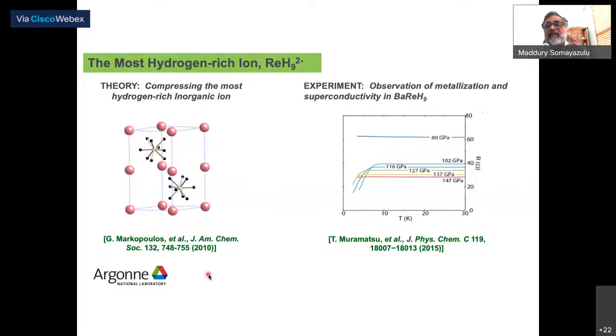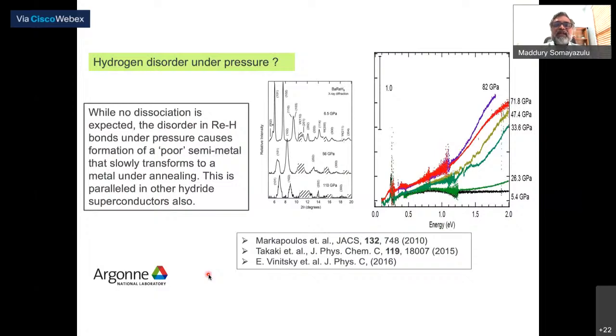But you realize that with increasing pressure, there are nebulous signatures of superconductivity, but not so superconducting. I mean, as you can see, the curves presented here seem to indicate that you do get a transition where the resistance is dropping, but things don't seem to be very good. Now, this intrigued us. I mean, there was nothing structurally we could find which said that it is wrong. I mean, with respect to where the theory goes and where the experiment goes, we are converging, but we are not quite there yet. And so the question we asked is, what is happening in these materials? And what is the reason that this is not happening here? And then we realized that we don't see a dissociation.